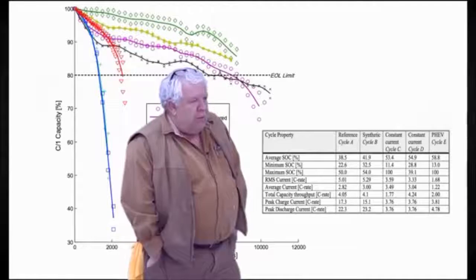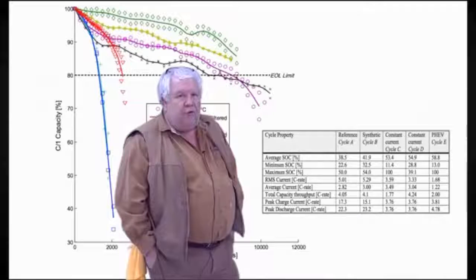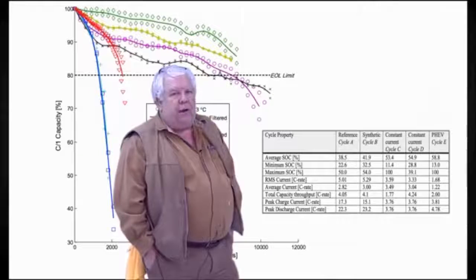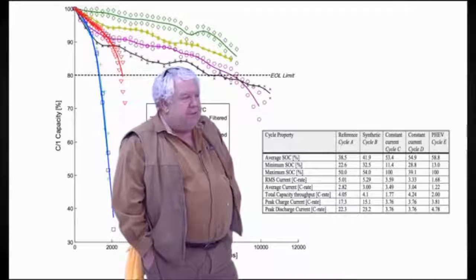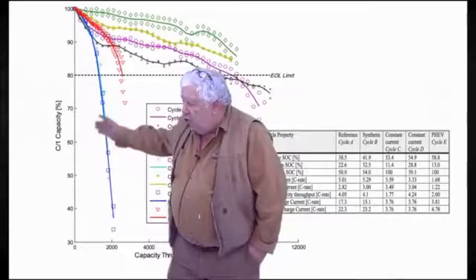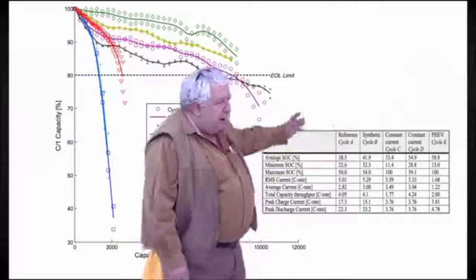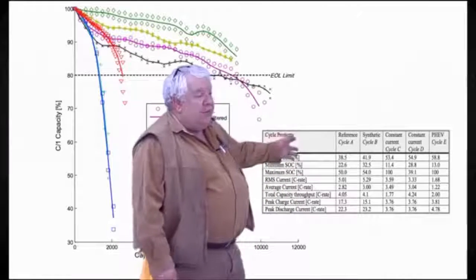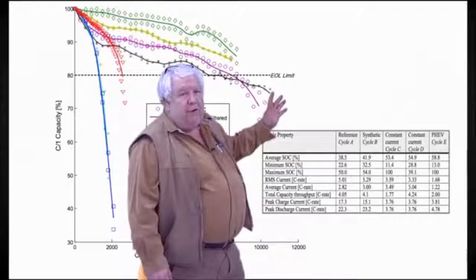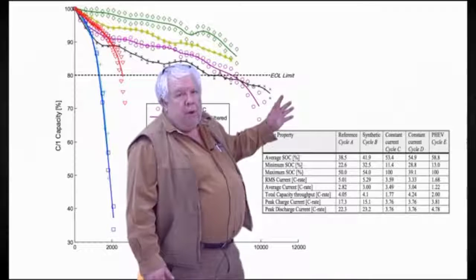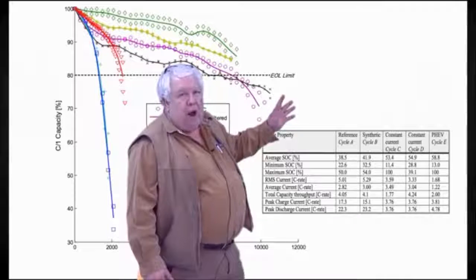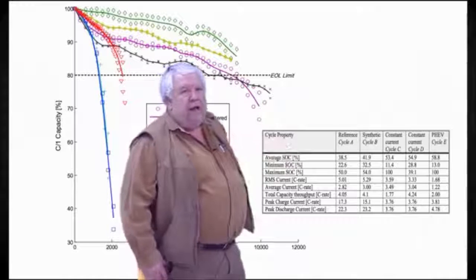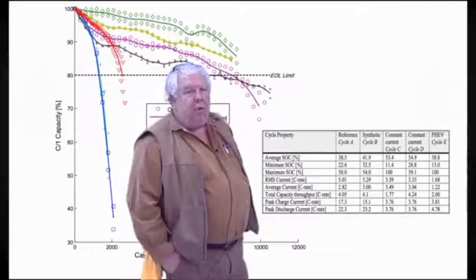And so the heavy current loads and temperature do not appear to be players in shortening the life, but fully charging the cell and fully discharging the cell does. Here's 2,000 cycles, here's 9,000 cycles. The 9,000 come as the results of charge and discharges, a map, a program derived. They took 40,000 data points from an actual bus drive and filtered them down to 2,000 seconds with a different value each second and ran that as a program.